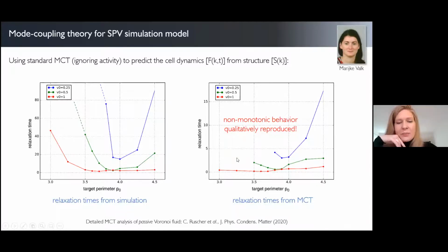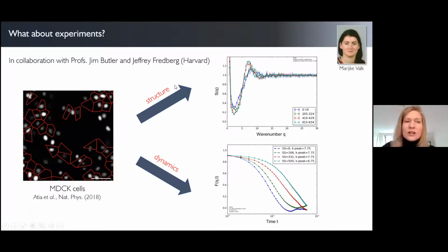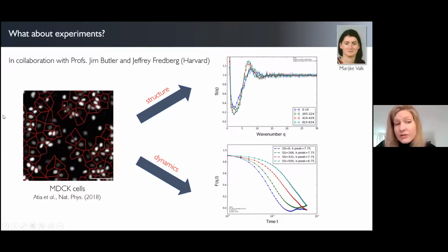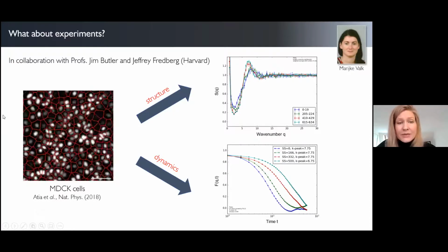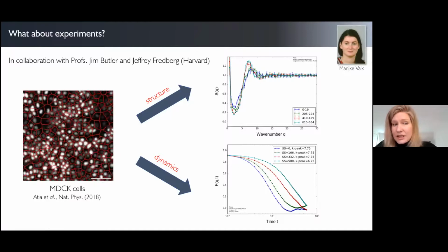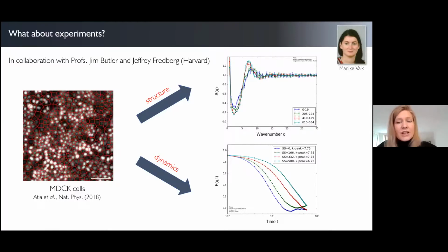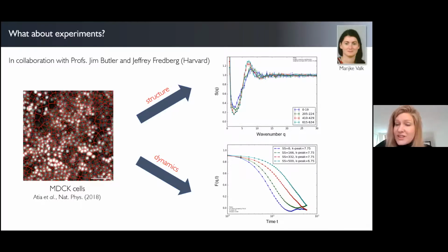And then finally, what about experiments? For that, Marijke spent a few months in the groups of Jim Butler and Jeff Fredberg at Harvard Medical School, who have these beautiful experimental cell data. Marijke extracted the static structure factors and the intermediate scattering functions from these data by looking at the positions of the cell nuclei over time.